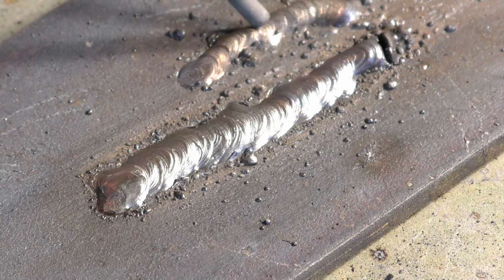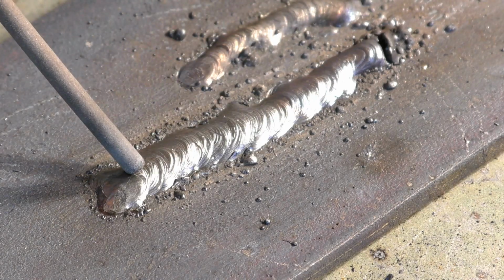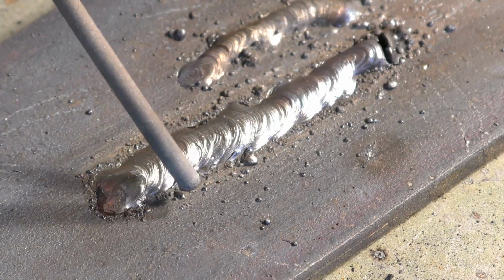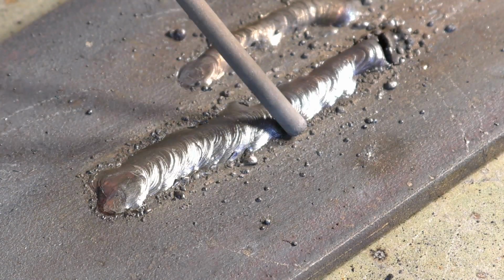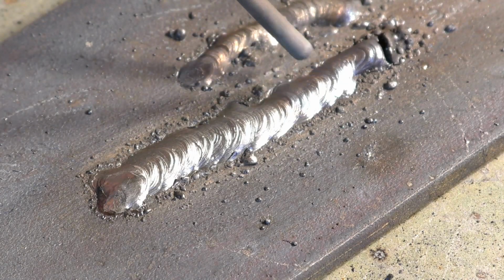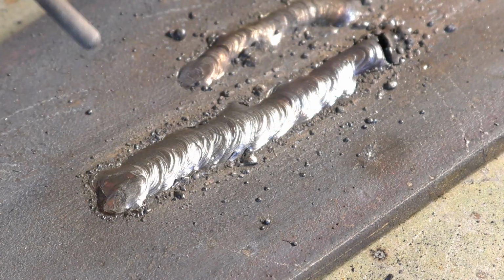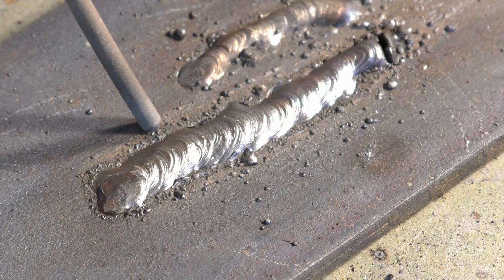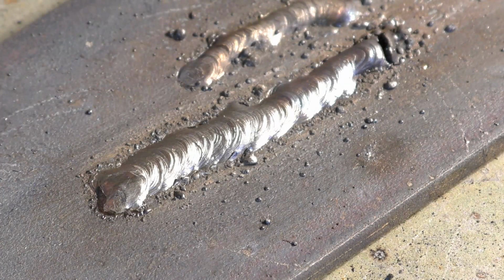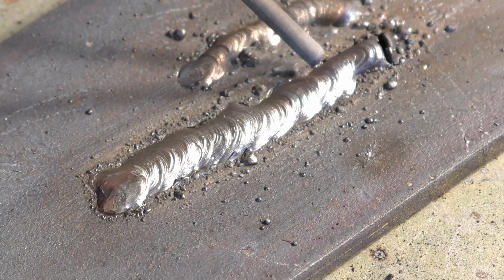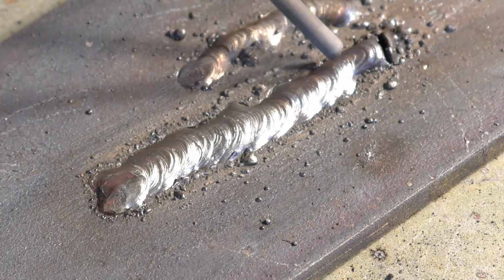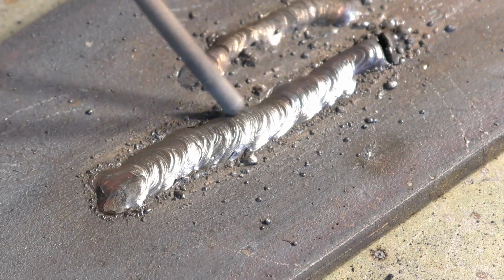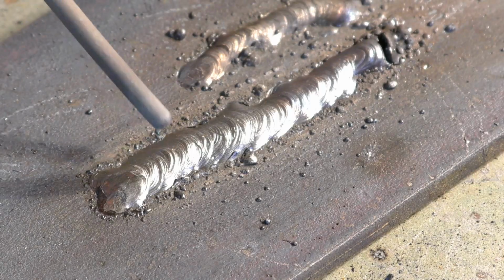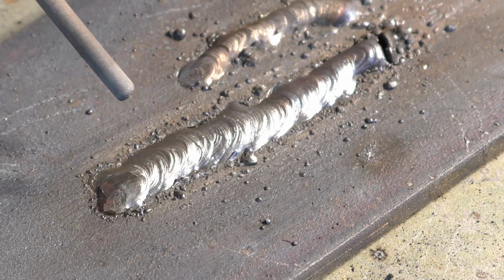You see the weld stands up on top of the material here, but in this example you can see at the edges it's just etched the material away very slightly. There is splatter here, but you're going to get splatter with stick welding whatever you do. You can minimize that, and there are sprays you can use on the steel before you start welding, but I never really used that myself. So you can see you can do a successful weld run. After all, that's what this is, just a weld run. But this is the way that you practice welding.